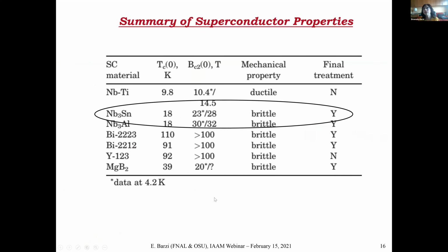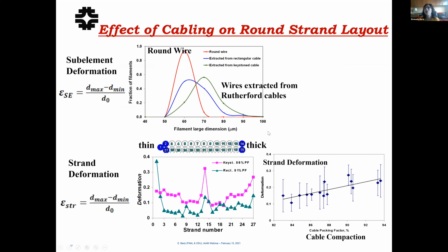So anyway, based on the field that we wanted to achieve of 15-16 Tesla, and based on the properties of both low temperature and high temperature superconductors, of course, the best candidate was Nb3Sn, which is why we did all this work with Nb3Sn. So then another problem that you have when you study these materials is that you cannot just look at the round materials. In US academia, they do a lot of studies on the microstructure of the round wire after heat treatment. But we have to go beyond that, because we have to put this wire, as you saw, in this Rutherford cable, and this generates very huge strains and deformation of the whole structure. And of course, it affects the microstructure.